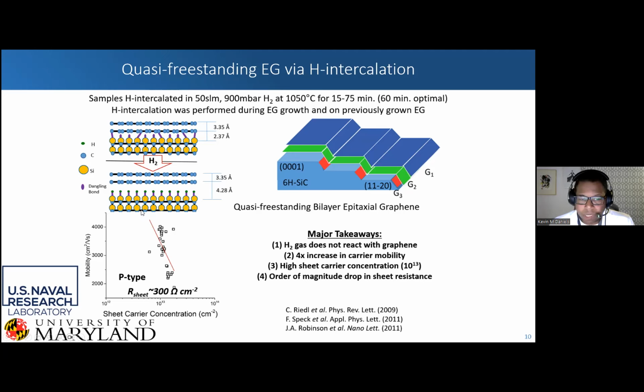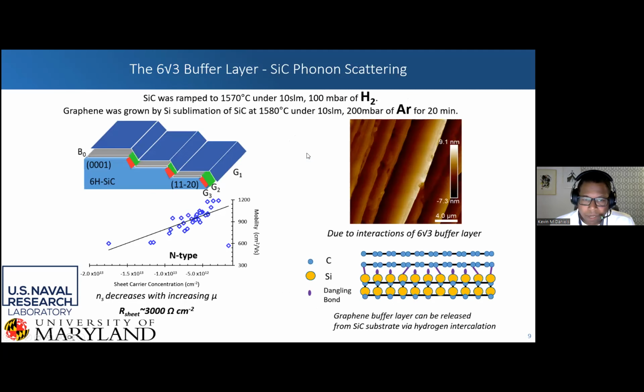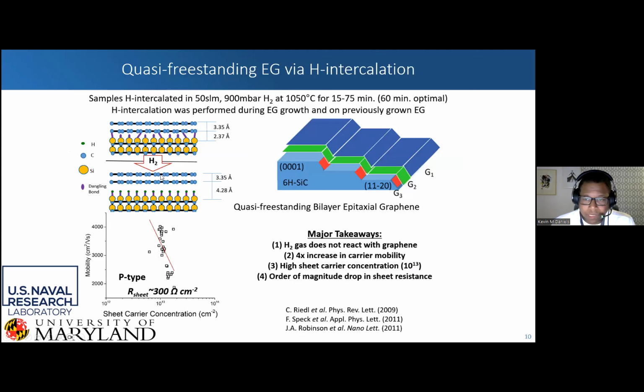When this data was taken, we're getting around 4,000. Now, folks at NRL are getting around 5,000 centimeters squared per volt second. One thing to note here is that compared to this area, where you have this buffer layer, and you have these 2 layers with quasi-freestanding, you're releasing this buffer layer. So now you have a pretty uniform 2-layer growth here. You really get optimally 2 layers of material when you intercalate monolayer graphene.